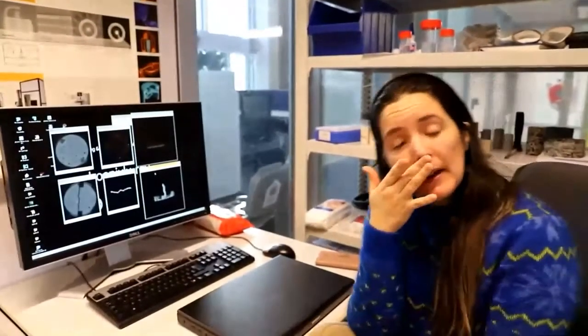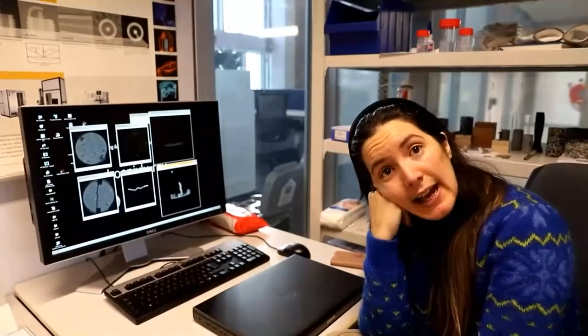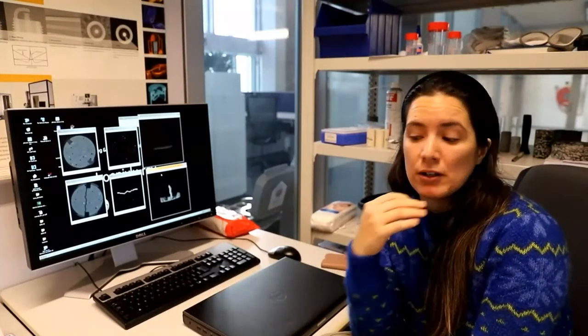Basically, I do the same technique. I scan the beam at a dry state and then at a saturated state, and I can map the porosity in the microbeam. In this case, we prefer to use smaller samples because the smaller the sample, the higher the resolution that we can obtain potentially, depending on the CT scanner, of course. In this case, we obtain a resolution of 500 nanometers per voxel. So then we simulated the permeability in this pore structure that we found with the CT scanner, and then we could also obtain tortuosity, and this gave us the input parameters that we needed for the transport model.